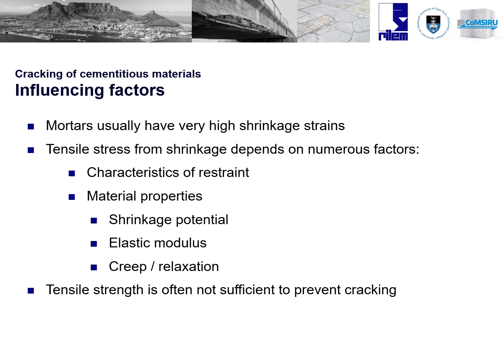In terms of shrinkage, patch repair mortars usually have very high shrinkage strains simply because they don't contain coarse aggregates, and often have a high cement content and a high water content. The tensile stresses that come from restrained shrinkage depend on a number of factors: the characteristics of the restraint, the properties of the material — in particular the shrinkage, the elastic modulus, and the creep or relaxation — and in all of this the tensile strength is often not sufficient to prevent cracking.